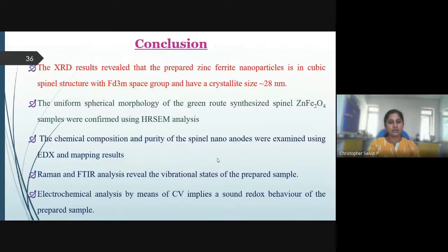As concluding remarks, we would like to highlight that the XRD results reveal that the prepared zinc ferrite nanoparticles are in cubic spinel structure with the Fd3m space group and have a crystallite size of approximately 28 nanometers. A uniform morphology of the green synthesized spinel zinc ferrites was confirmed with the HRSEM analysis. The chemical composition and purity of the spinel ferrites were examined using EDAX and mapping results. Followed by that, Raman and FTIR analysis reveal vibrational states of the prepared sample. Electrochemical analysis by means of CV implies a sound redox behavior of the prepared sample.